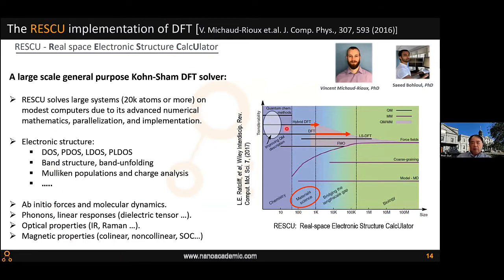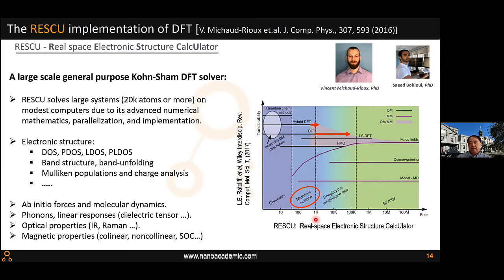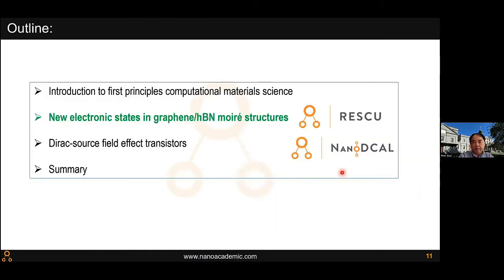By innovating this computational mathematics, we have pushed density functional theory calculations to many tens of thousands of atoms — typically 20,000 atoms, with the largest run exceeding 100,000 atoms for some projects. Before around 2017, first principles material science was limited to roughly 100 atoms. By breaking this bottleneck, we can now push into the real application domain. So now I'm going to use these tools to study something new: graphene moiré structures.